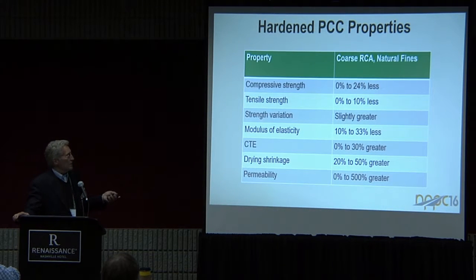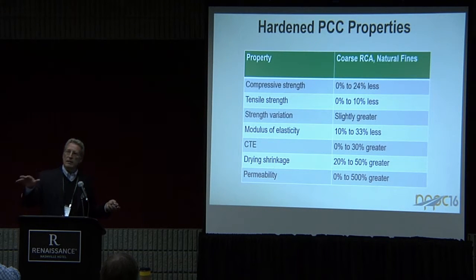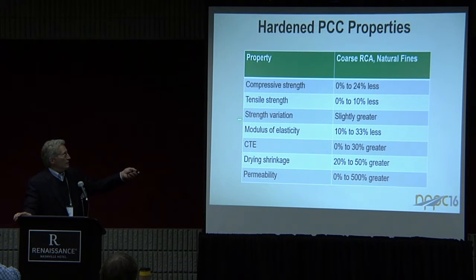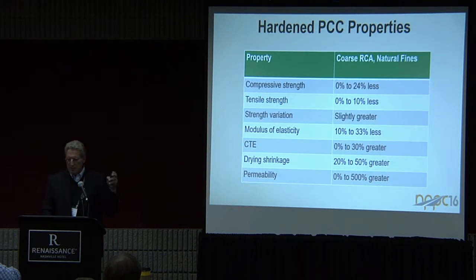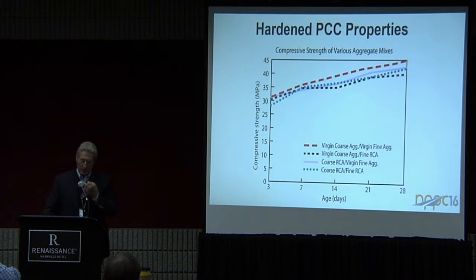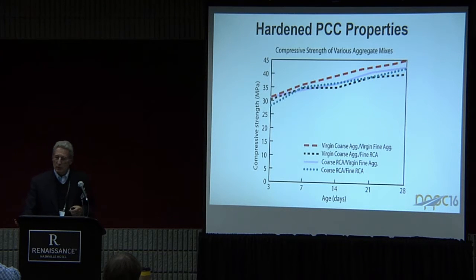In terms of our hardened properties, again, depending upon how much mortar you clean off and the mortar content, might be anywhere from the same strength to as much as 25% lower if you don't change anything else to compensate. Same thing for tensile strength, a little higher strength variation, a little lower modulus of elasticity, potentially higher thermal coefficient, potentially higher drying shrinkage, and potentially much higher permeability. So these aren't necessarily stoppers, but they're things you need to be aware of, need to characterize, and maybe address in the mix design. With lower water cement ratios, for example, to tighten up the pore structure and increase the strength.